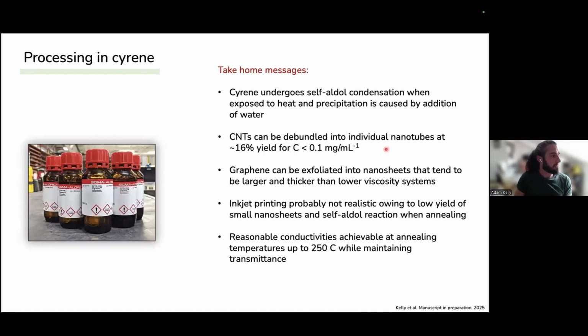So the take-home messages, if you want to work in Cyrene, is that it undergoes this condensation when exposed to heat. So you need to work at low temperatures to avoid it, if possible. Carbon nanotubes can be debundled into individual nanotubes, but the yield is about 16% for concentrations below 0.1. We can exfoliate graphene into nanosheets, but they tend to be larger and thicker because of, again, the viscosity of the Cyrene. Inkjet printing is probably not viable because of the low yield of very small nanosheets that are printable.